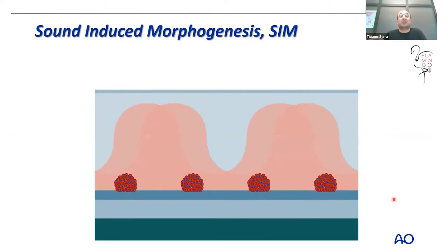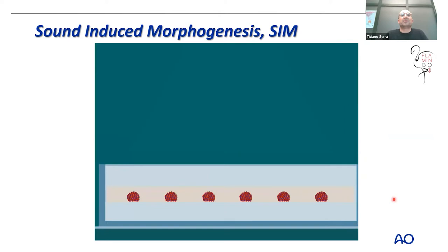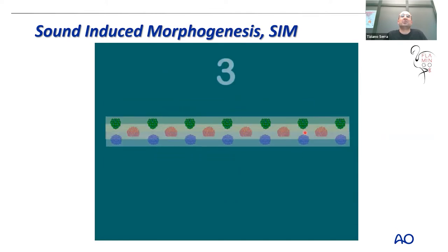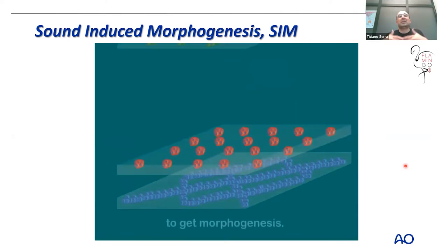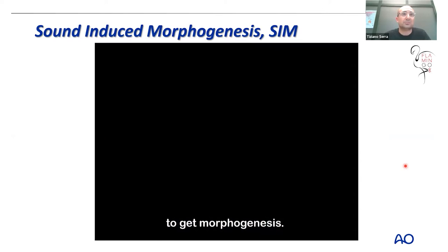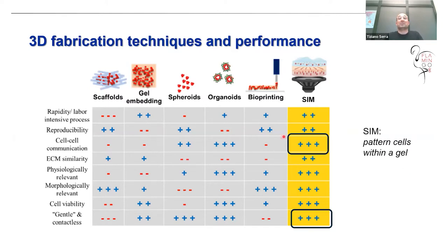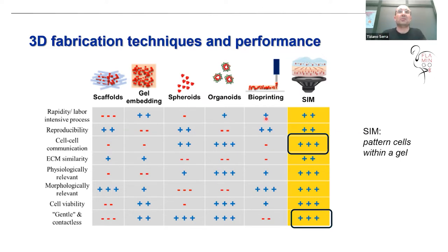We can then cross-link using light or enzymatic or pH-based methods, and customize all shapes by quickly changing the frequency, amplitude, and chamber shape. It's as easy as a sea wave, but with cells. We could also stack different layers one on top of the other, changing the cells, hydrogel composition, and chemistry to enhance hierarchical tissue generation. Compared to existing technologies, SIM provides much higher cell-cell communication since it aggregates cells close to each other — a bio-assembly approach that is also very gentle and contactless.